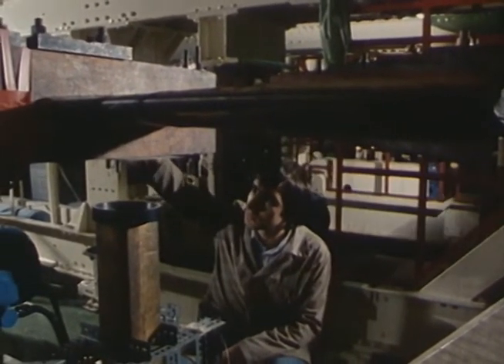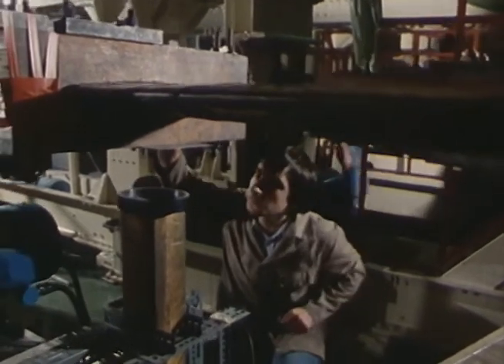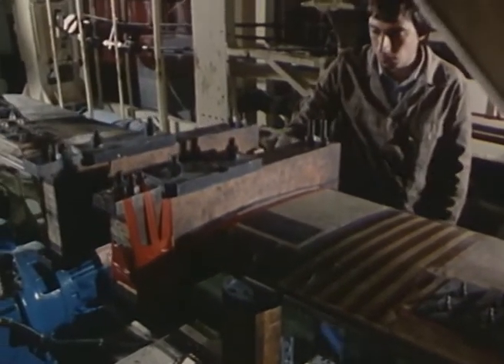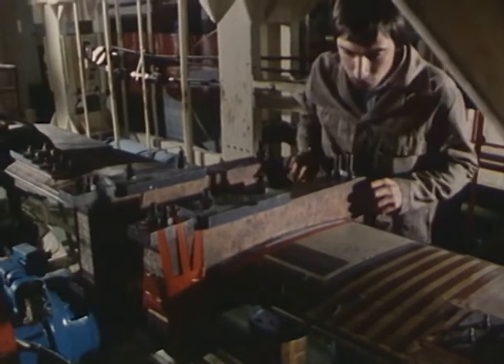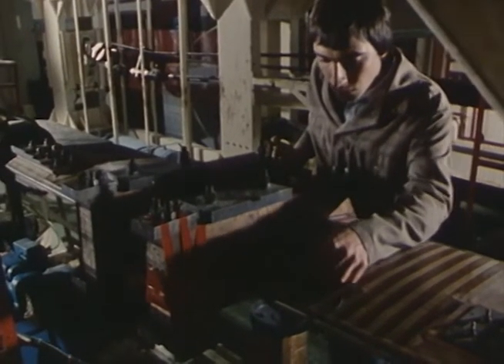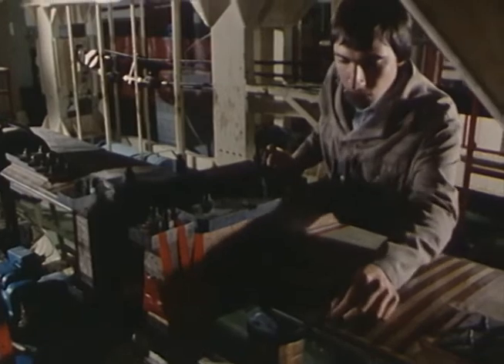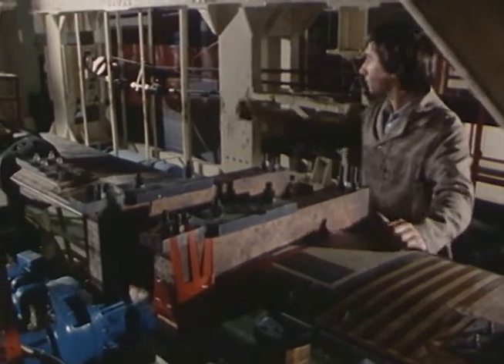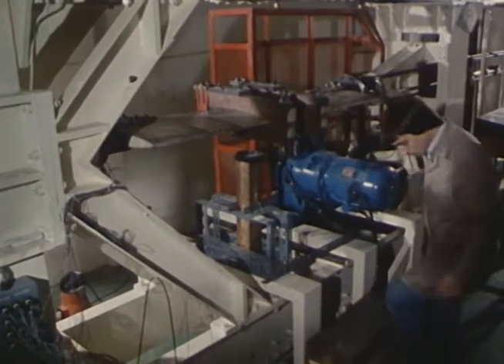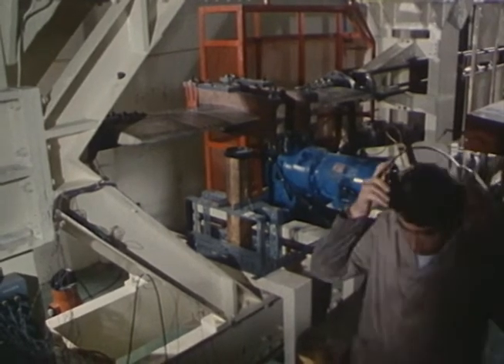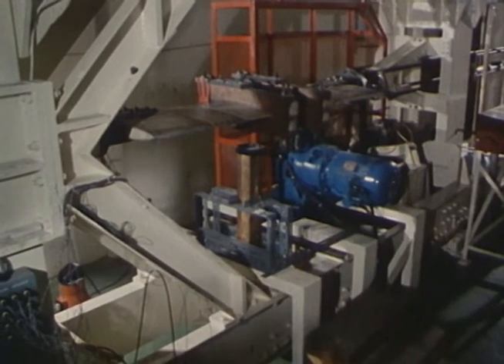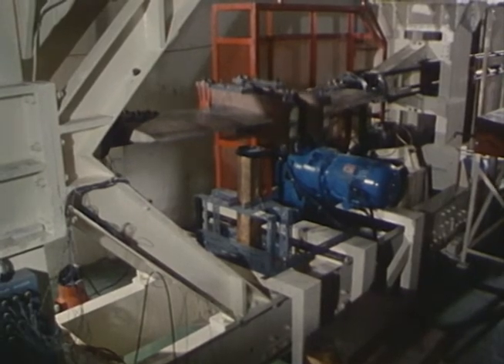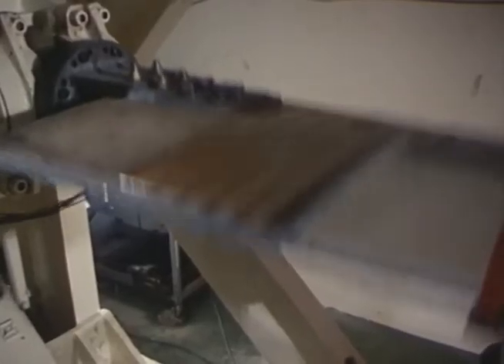Blade design was backed up by an extensive program of structural testing. Basic material properties and blade strengths were determined by over 2,000 specimen results, 470 structural elements, and 60 full-size blade sections. This testing has confirmed that the safe fatigue life of a composite blade is at least 4 times that of a metal blade, with the potential for unlimited life. Structural testing reproduces the most severe loads produced by manoeuvres such as flaring to hover, highly banked turns, and recovery from sideways flight.